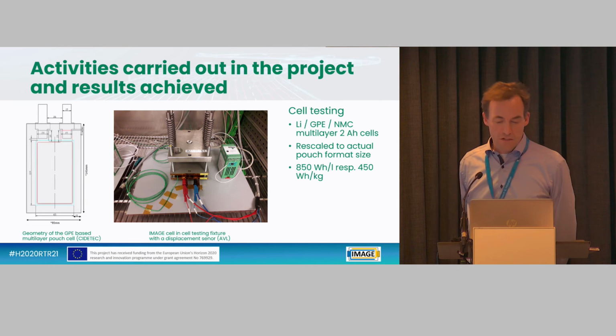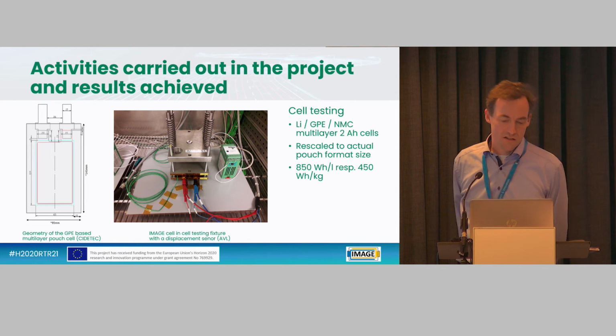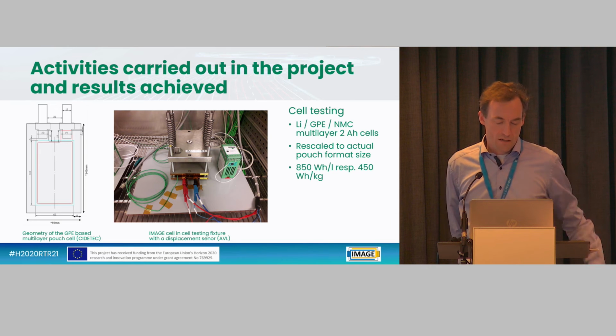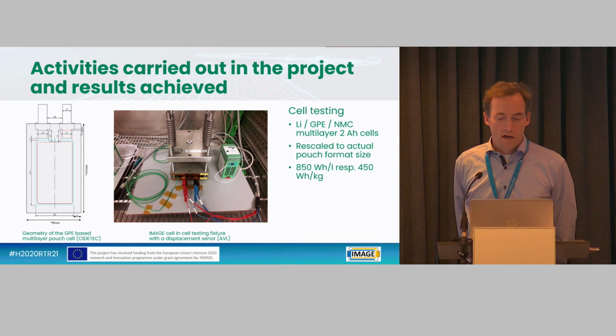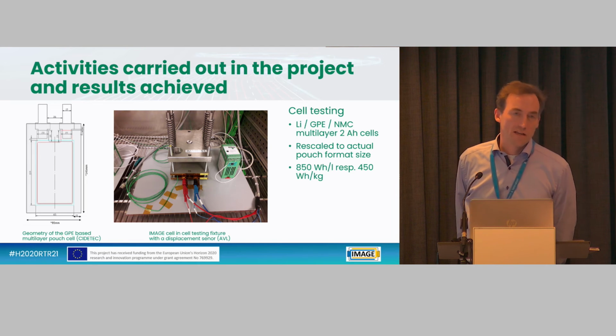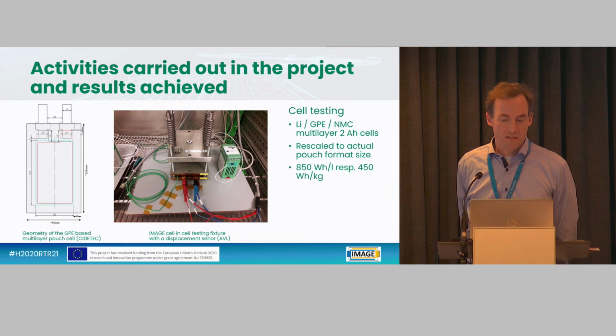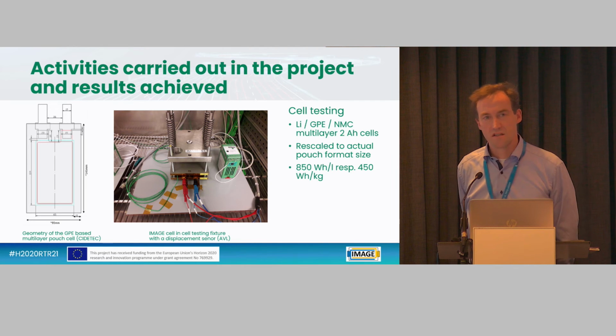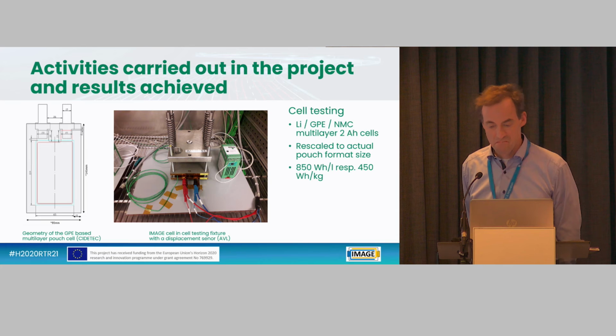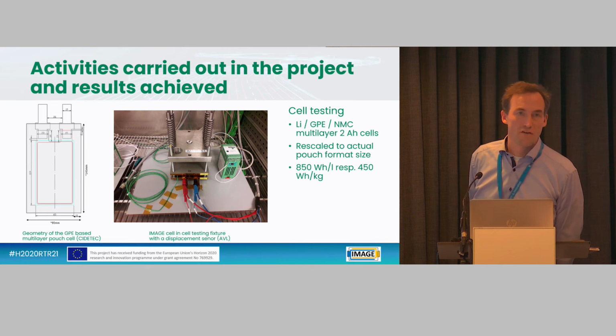I put in one of the pictures showing one of the cells from CIDETEC in a fixture which is measuring the volume changes. As a takeaway, if you upscale one of our 2 ampere hour cells, rescale it to a modern 60 ampere hour cell, a volumetric energy density of 850 watt-hours per liter is possible, also 450 watt-hours per kilogram. However, for the cells we could build in our project, the cycle number is not good enough for the automotive industry at the moment.